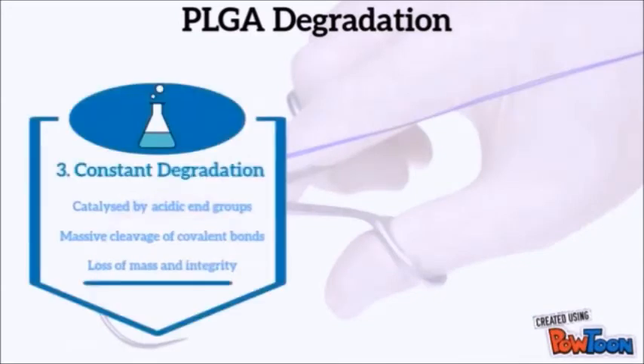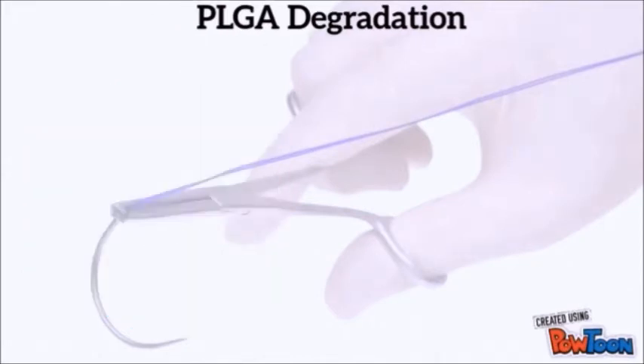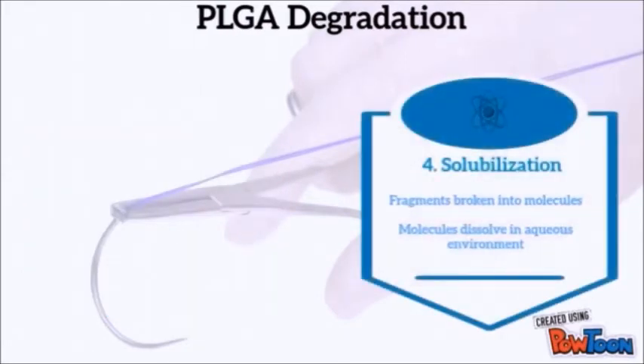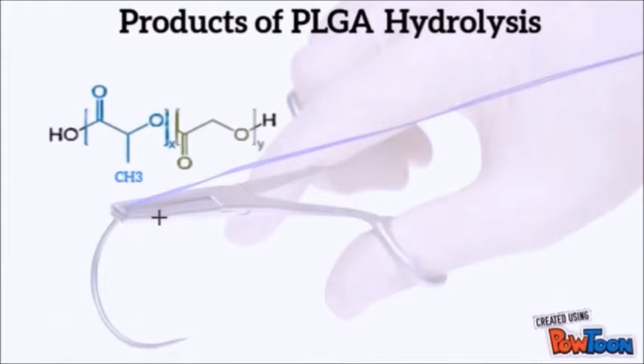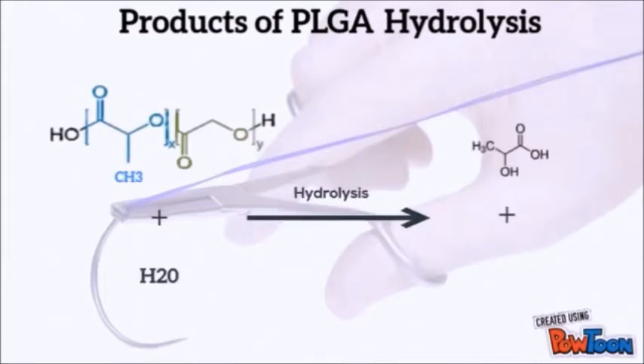Step 3 is constant degradation, which is when the degradation process starts being autocatalyzed by carboxylic acid end groups. This results in massive cleavage of the covalent bonds in the polymer backbone, resulting in a loss of mass and integrity. Finally, step 4 is solubilization, where the fragments are further cleaved into molecules which are soluble in an aqueous environment. Hydrolysis turns PLGA back into lactic acid and glycolic acid, which naturally occur in the body.